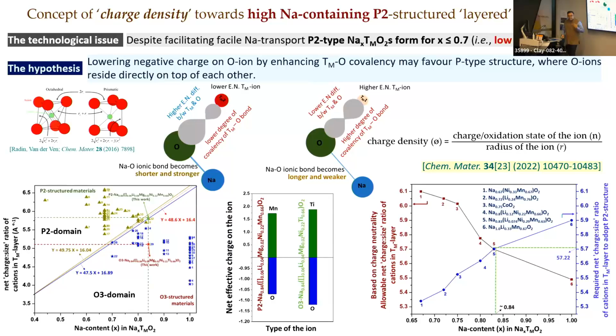Now again, one cannot simply design a transition metal layer with a high charge to size ratio and at the same time keep increasing the sodium content, because charge neutrality has to be taken into account. While on the transition metal layer, one is increasing the charge, one cannot keep increasing the sodium content. That also has a positive charge, right?